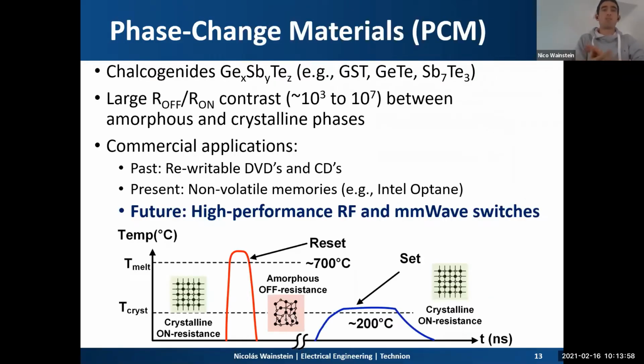So phase change materials are the active material and the fundamental material in the IPCS, or again, the indirectly heated inline phase change switch. PCM chalcogenides are compounds of the ternary of germanium, antimony, and tellurium, which present a large resistivity contrast between the amorphous and crystalline phases. These materials are not new and have been used in the past for rewritable CDs and DVDs. They are currently being used for non-volatile memories such as Intel Optane for persistent memory and storage class memory. And it has been foreseen that in the future they will be used for RF, millimeter wave, and optoelectronics applications.